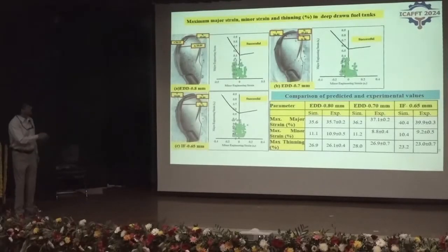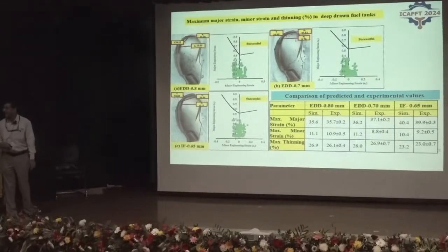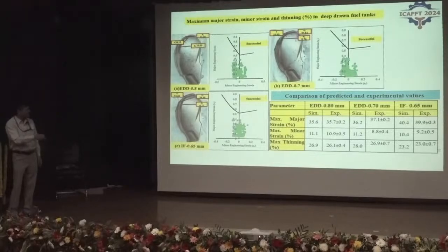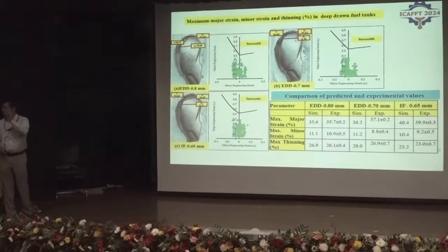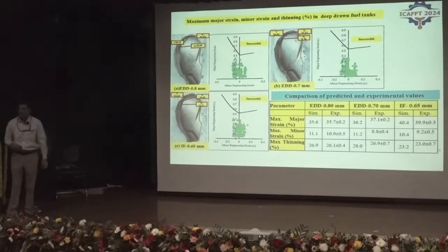So we can see the comparison between experimental and simulation results for different grades and different thicknesses. And experimentally also we have seen that EDD with 0.7 and IF with 0.65 can be safely formed without any failure. And these are the simulated and experimental results for maximum major strain, maximum minor strain, and maximum thinning. So within a small discrepancy, the predicted results agreed well with the experimental results.